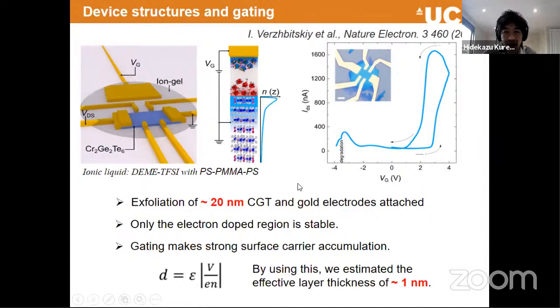The other thing I want to highlight is although we start by gating a 20 nanometer thin film, because of the huge doping, we can accumulate lots of charge on the surface, and the thickness of the conduction channel is about 1 nanometer when you plug in the doping density and the constant voltage, and then it quickly calculates this distance or width of this channel, d. So this is interesting because we didn't start with a one monolayer regime, but effectively we make something close to a two-dimensional electron gas by using this technique because of the large electric field we create by the ionic gel.